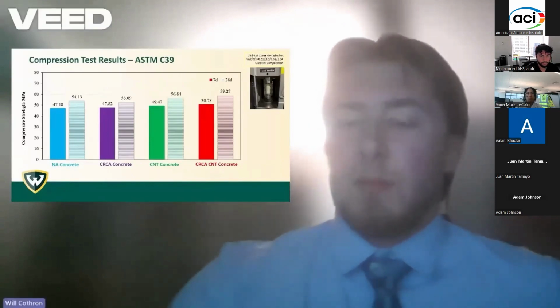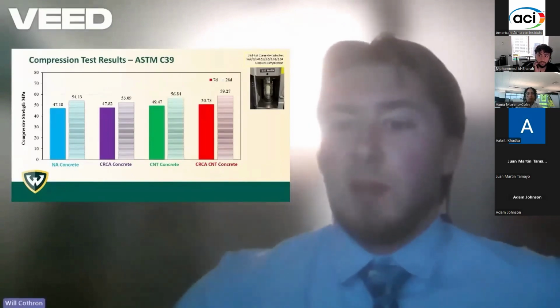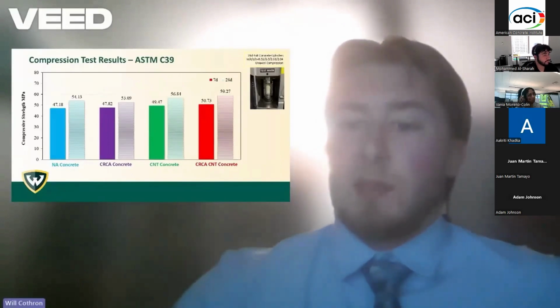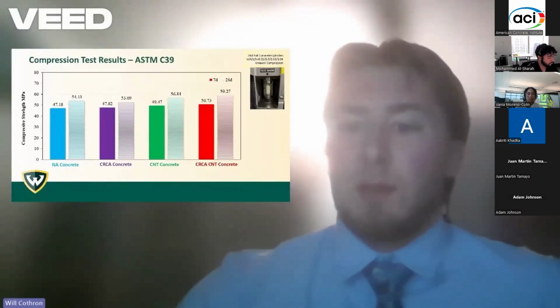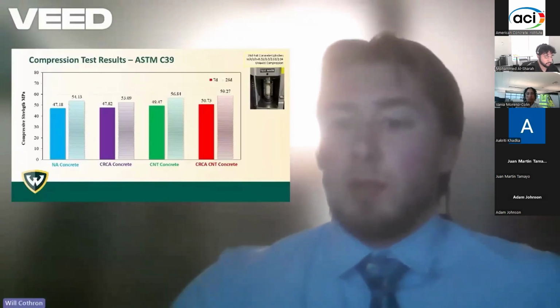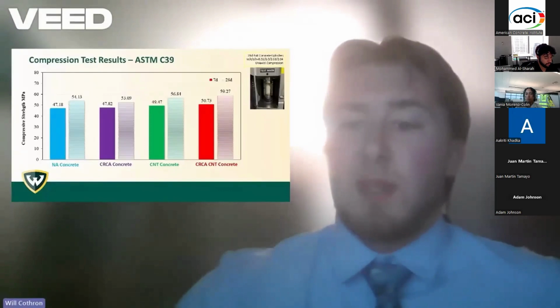To assess how our concrete mixes performed in terms of strength, we conducted compressive strength tests on cylindrical samples following ASTM C39. We tested the samples at 7 days and 28 days. Natural aggregate concrete showed approximately 47 MPa at 7 days and 54 MPa at 28 days.